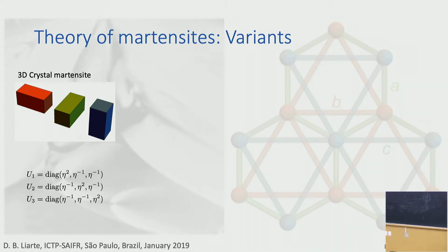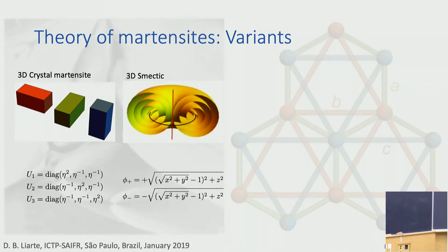That's right. I've chosen one Martensite transformation where the volume is kept constant. And that's why you have eta square, eta minus 1, and minus 1 there, so that the determinant is 1. So the volume is kept constant. So these are the variants for the crystal Martensite. For the Smectics, we choose the variants to be this 3-dimensional toroidal focal conic domain. I had shown you before another kind of focal conic domain where you have an ellipse and a hyperbola. But you can think of a simpler case where you just have a circle and a straight line. The ellipse becomes the circle and the hyperbola becomes a straight line passing through its center.